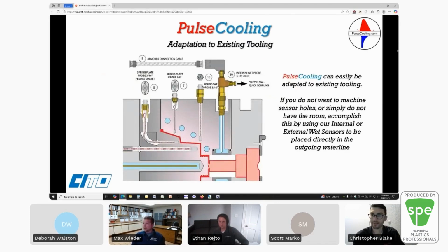We have multiple sensor styles available based on the complexity of your tool. A simple drilled hole will accommodate our mold steel sensors you see here on the left. These sensors are used to get as close as possible to the molding surface for real-time feedback. If you do not want to modify your tool or simply don't have the room, we can utilize our sensors to be placed directly into the water line here. This is our internal wet sensor with a quick connect flow-through coupling. The sensor length here is determined on where you want the reading to take place. Obviously, closest to the molding surface will optimize your results. We've had guys put them in eye bolt holes and lift mount holes, and just because they are reading that real-time temperature of the mold steel, they still were able to optimize their cycle times.